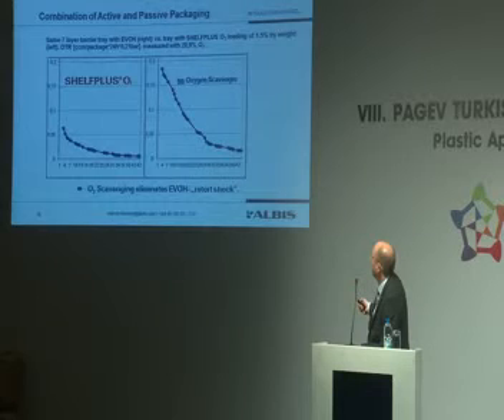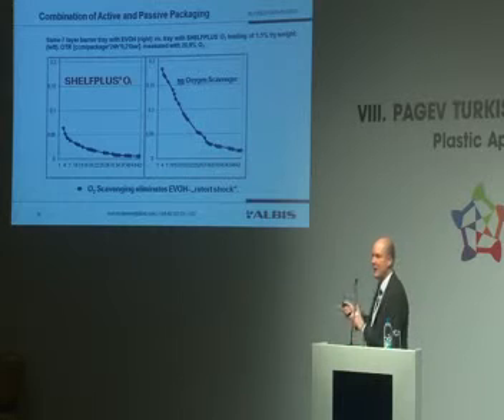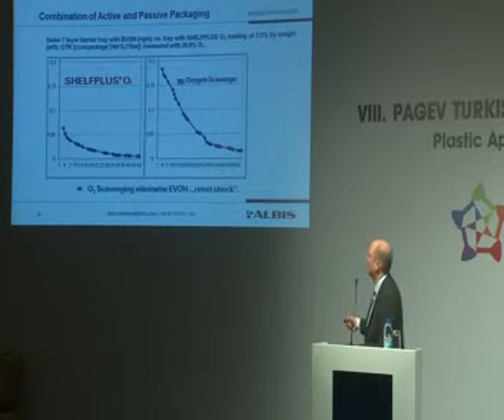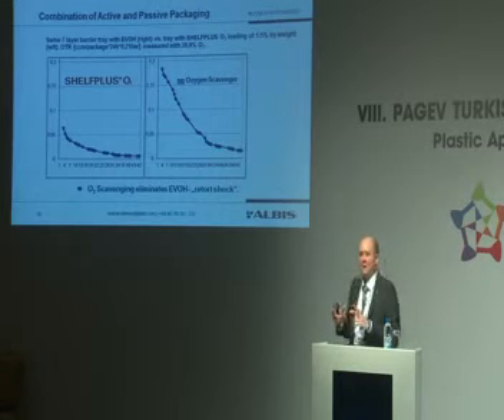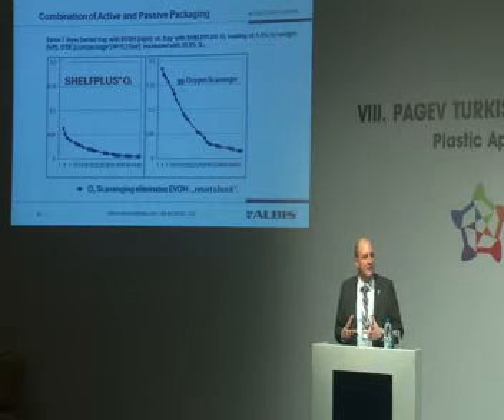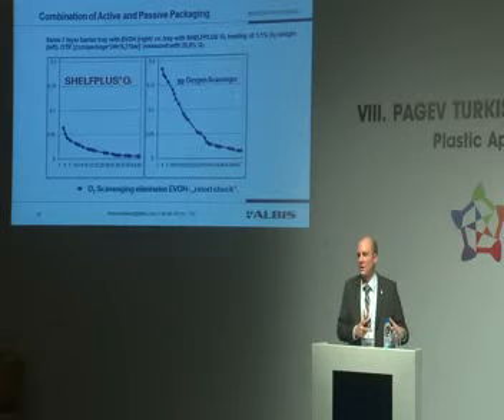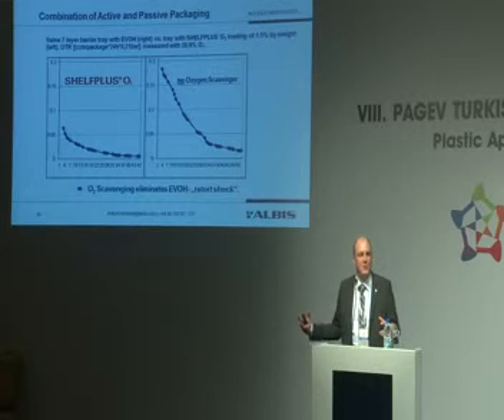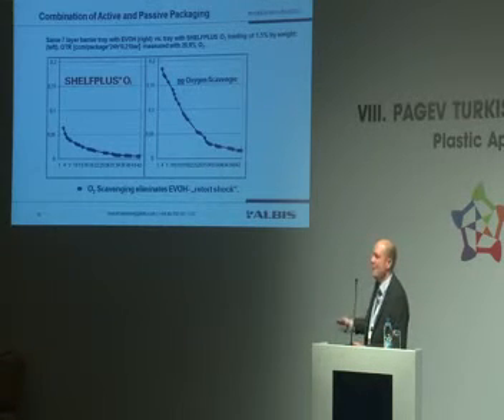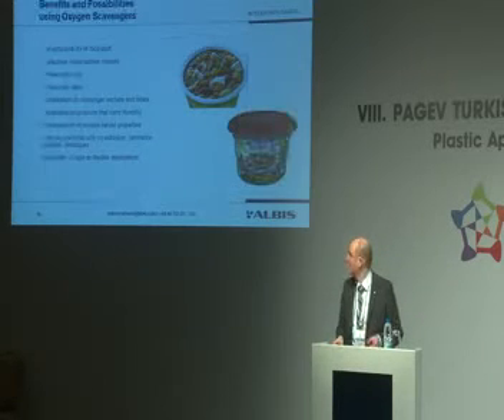So if you have an application with no oxygen scavenger, just EVOH, in the first days after production, your OTR, so oxygen transmission rate, is rather high, and only after 28, 30 days, you reach those values of 0.05, which are the target for the application at the end of the day. Now, if you combine this together with an active oxygen scavenger, you completely avoid this effect. You remain at this low level of 0.05 OTR from the very beginning. So we can even say that if your target is not to reduce the amount of oxygen that was inside the packaging, but only to keep oxygen from coming in, this is a real safe way to do so if you are talking about EVOH.